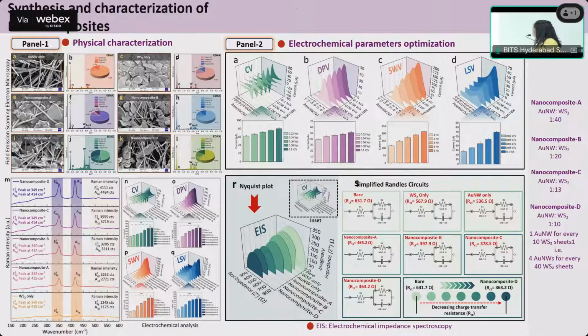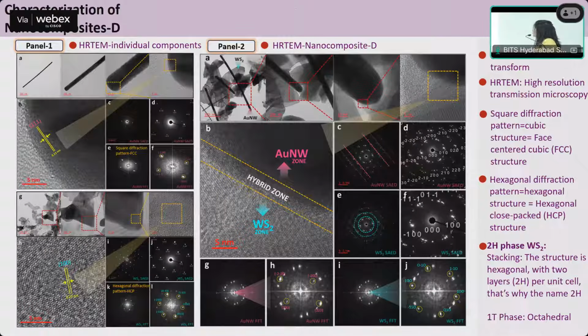And this is the electrochemical spectra like CV, DPV, SWV, and LSV of different nanocomposites together with the control, which suggests that nanocomposite D is better in all the parameters. And optimization studies were again carried out in this case, as mentioned previously, that's the EIS spectra. And the morphological analysis by HRTEM suggests that this is the nanowire structure at different magnifications. And here you can see it's at 0.23 nanometers of spacing for the 111 plane, which is corroborating with the SAED spectra and the FFT spectra in the cubic structure.